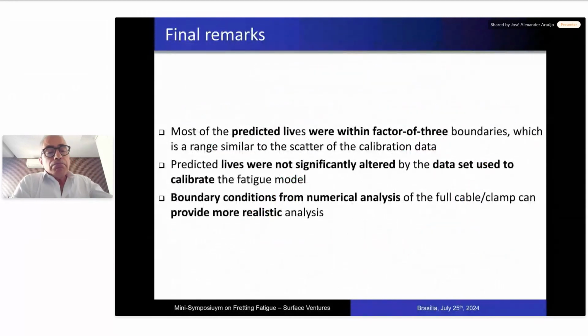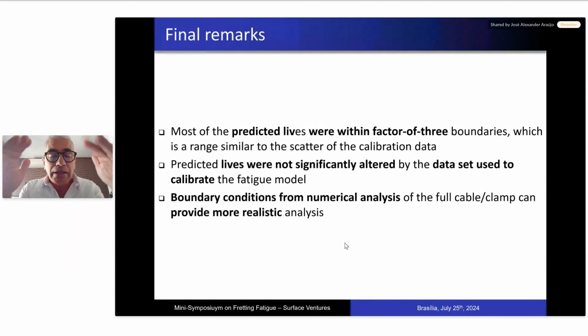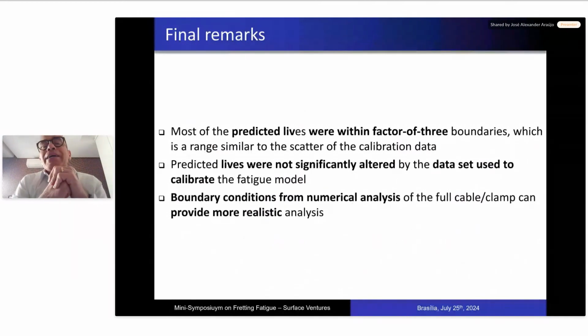And to conclude, basically the lives estimated were quite satisfactory within factor boundaries of 3. And these estimated lives are not altered by the data used to calibrate the fatigue model, either if it's a V notch or a hole notch. The lives were very similar. And well, at last, to conclude, the idea is that we can get the normal loads, the shear loads, and the bulk fatigue loads that will occur in one single wire, doing a finite element analysis of the full cable clamp, and then extract them and use this methodology to predict the lives for the wires.